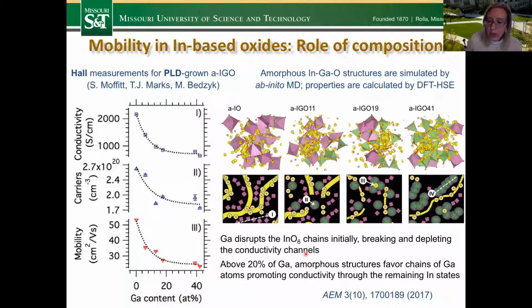But above 20%, what we see is that the structures favor the chains of gallium itself. And although gallium does not really contribute to the conductivity, it promotes the conductivity through the remaining indium states. It's a weaker conductivity, of course, a bit weaker mobility, lower carrier concentration, but still just simple morphology really helps explain the observation of the properties in these materials. And so it should be considered, as well as the local structure, the longer range, medium range structure needs to be considered as well.